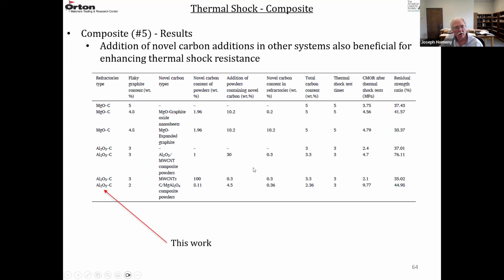So I mentioned there's other studies of what they call novel carbon additions. These are nanocarbon additions to other refractory systems, and they're all saying they're beneficial in terms of improving the thermal shock resistance. So here was an MgO carbon system with 5 weight percent graphite flakes, and then this is an MgO carbon with 4.0.